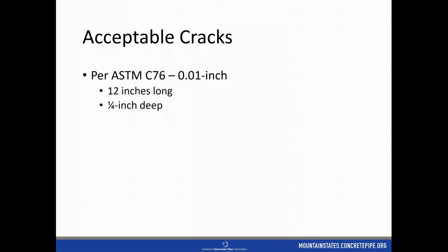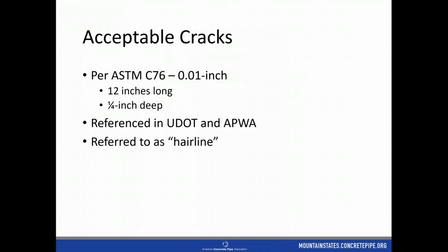So if you can't even get a 100th of an inch leaf gauge in it, a 1/4 of an inch, then that's even less than a 100th of an inch crack. That's even smaller, so obviously it would be acceptable there. These are both referenced in UDOT and APWA specs, the ASTM C76. So if you're using APWA or UDOT specifications, you can allow a 100th of an inch crack. Those are acceptable cracks, and it is often referred to as a hairline crack.